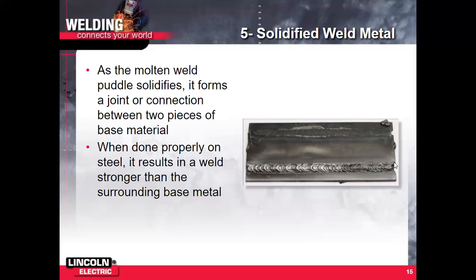And there's a weld here, but you can see the bluing line right here. Welds are going to break there. It won't break on the weld. It's very, very rare that a weld breaks in the middle of a weld. Usually the steel base metal has a strength of about 45,000 PSI, and this is going to be 70. So at minimum 70.